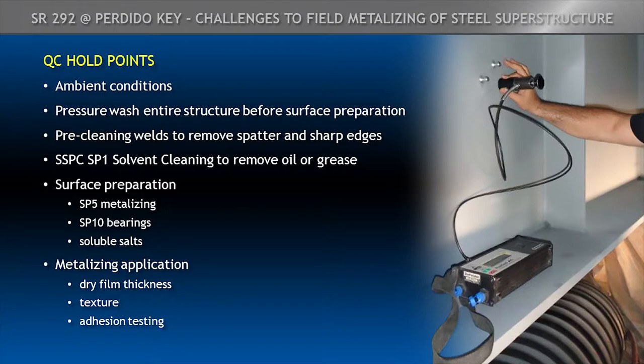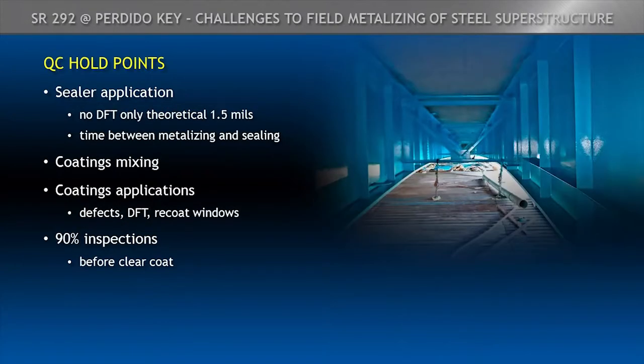We checked for texture, and then we did adhesion testing, as you can see in the picture here. Sealer application, there's really no DFT check for the type of sealer we used. It's only supposed to be a theoretical mil and a half to fill the porosity of the metalizing. And then we had to monitor the time between metalizing and sealing, and you'll see a slide or discussion here in a little bit how we handled that problem to move the project along.